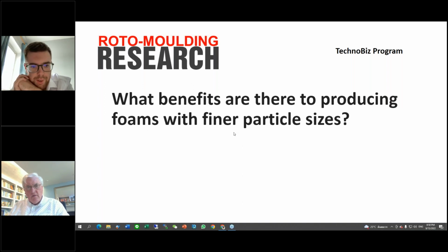Okay, and the next question then is, what benefits are there to producing foams with finer particle sizes? Which actually goes back to another thing that me and Martin were discussing there. To be able to produce an optimum foam, you need to make sure that the bubbles that you have remaining from the densification process are completely removed, because the gas that's produced during the chemical blowing agent decomposition tends to target those bubbles that are remaining and it makes them really coarse.